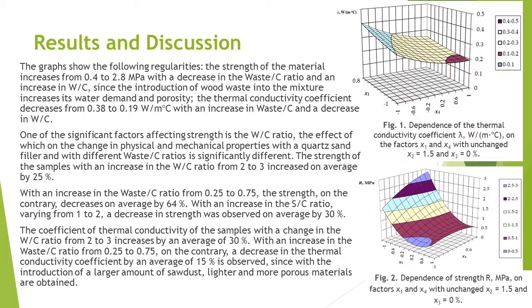One of the significant factors affecting strength is the water-cement ratio, the effect of which on the change in physical and mechanical properties with a quartz sand filler and with different waste-cement ratios is significantly different. The strength of the samples with an increase in the water-cement ratio from 2 to 3 increased on average by 25%.